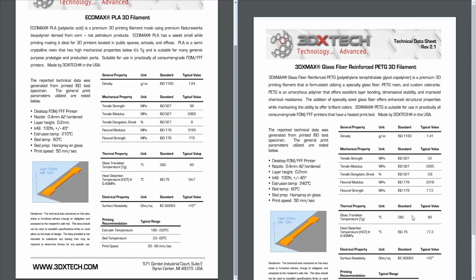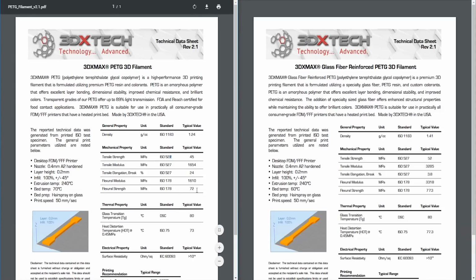So with this, if it's in tensile, then you would pick that obviously over the PLA, and it's slightly higher. Glass transition temperature is higher than PLA. Flexural modulus is higher than PLA. Flexural strength not as high, but it's got half the tensile elongation. So the fibers definitely lower it. So let's compare it to the standard PETG and the high temp. So quite a bit of improvement here. So we're gonna look at the improvement.